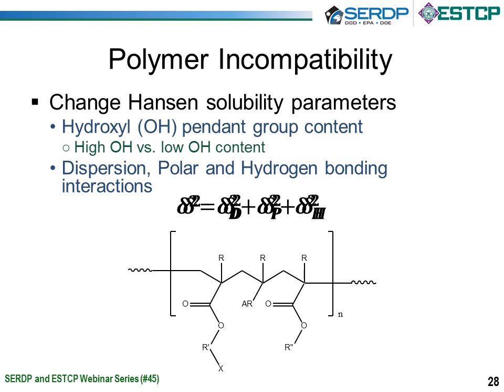In slide number 28, we utilized polymer incompatibility. Specifically, we wanted to take advantage of modulation of Hansen solubility parameters, and we were utilizing polyols by modulating the hydroxyl pendant group content. In one case, we were looking at fairly high OH content and combining those with low OH content polyols in order to try to achieve a phase separation or incompatibility. By modulating the Hansen solubility, we can exercise control over dispersion, polar, hydrogen bonding, and other interactions. So this ability to mix and match definitely played in our favor for this application.